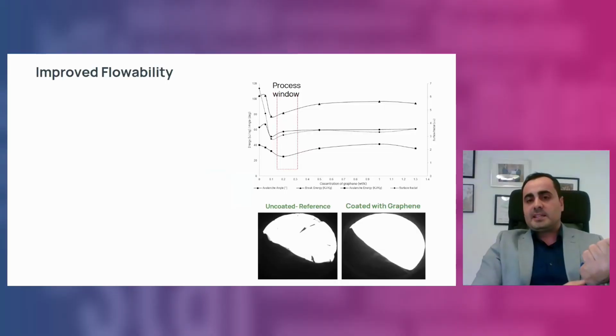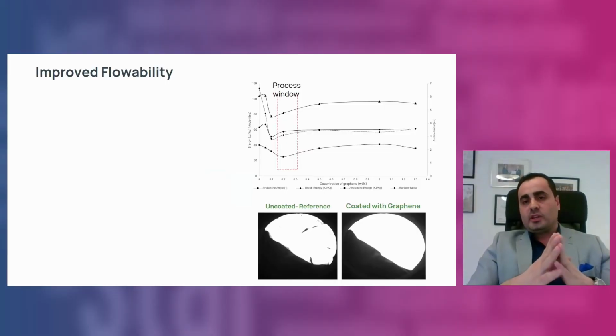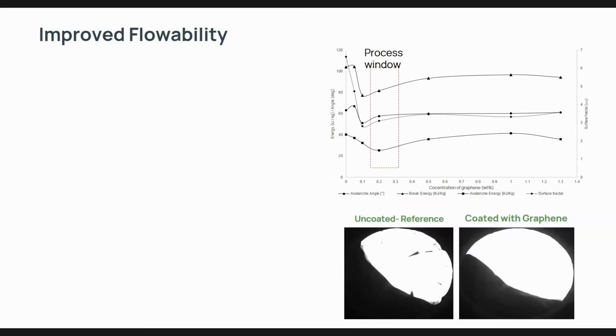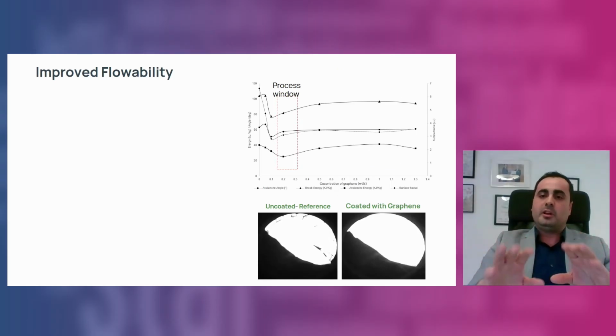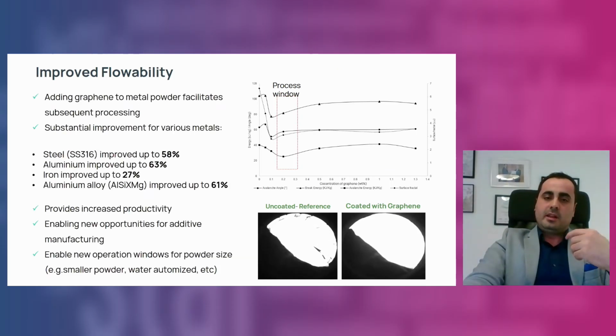So here you can see an example of steel coated with graphene in different concentrations and how the flowability has improved. When you don't have graphene, the flowability is a problem. And why is flowability a problem? Because in some processes like additive manufacturing, you need to build the powder bed. And if the powder doesn't flow, then you have trouble there. You can't proceed in processing the material. So by improving the flowability, you enable the processability.